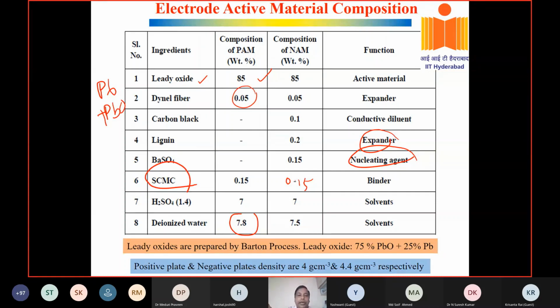And sometimes to improve the formation efficiency, I told you 3 cycles it takes. It's a huge time. 3 cycles means almost 4 or 5 days you have to wait for a lead acid battery to get ready. From an R&D point of view, it doesn't matter. For a commercial point of view, we think of 1 cycle versus 3 cycles. How much current you are spending, how much labor, manpower, electricity, and other time you are using. You can avoid that minimum 4 or 5 days of time if you can increase the formation efficiency.